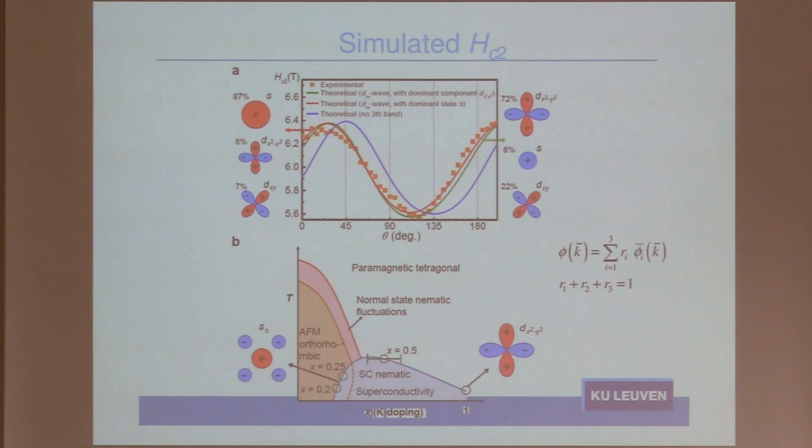If you take the mixing of only S and D, x square minus y square, we obtain this blue line, which is exactly 135. So if you combine this and this, you'll obtain some maximum going in a perpendicular direction. Well, they are both equivalent. But this still doesn't coincide with the experimentally observed curve. That is why we admix the third state. If you admix one more state of this type, then we can reproduce the experimental second critical field.